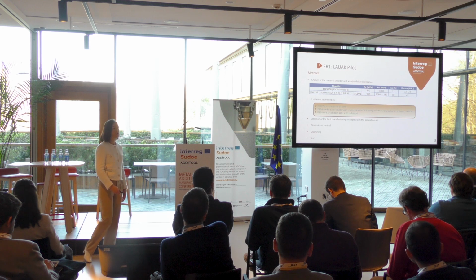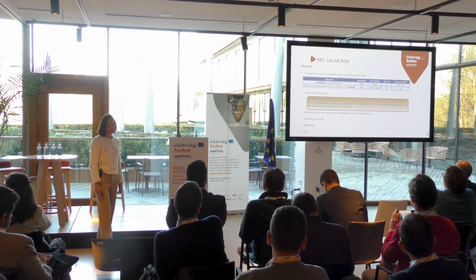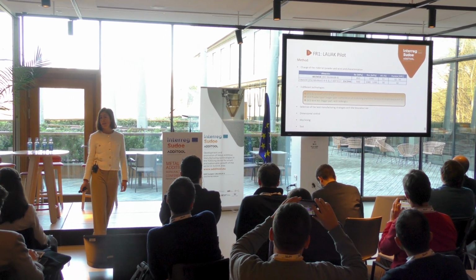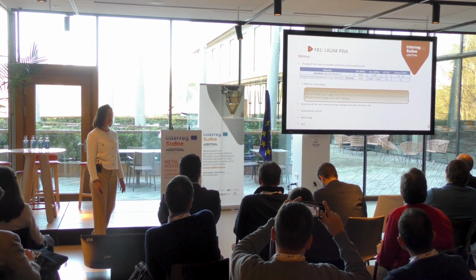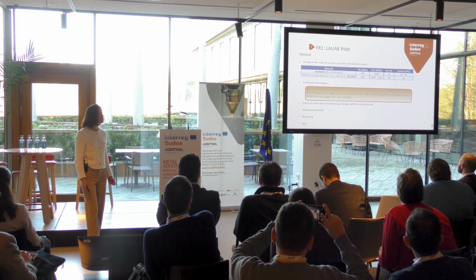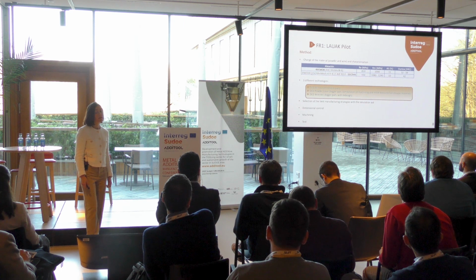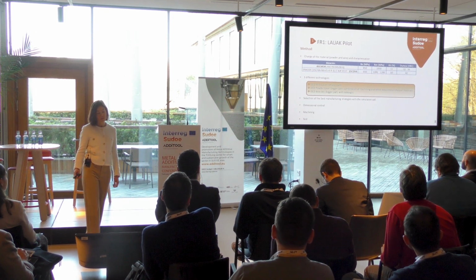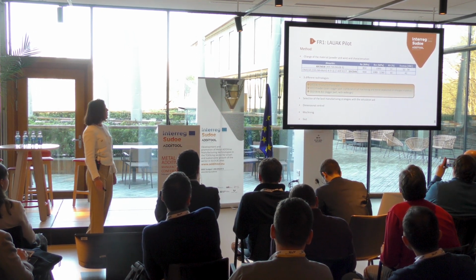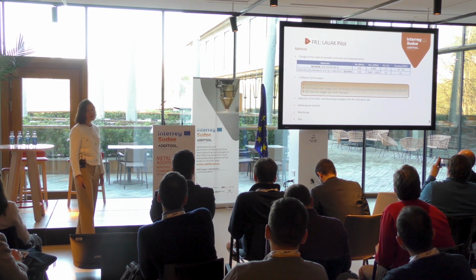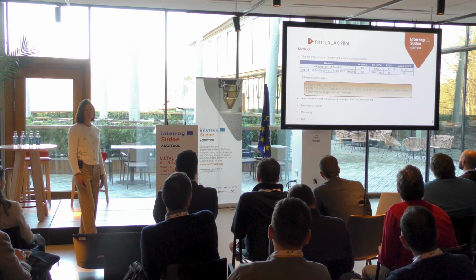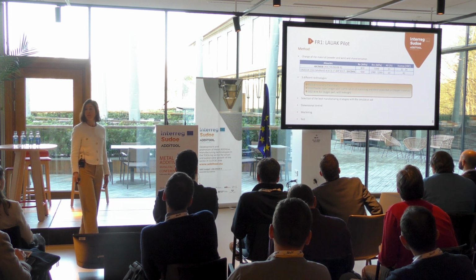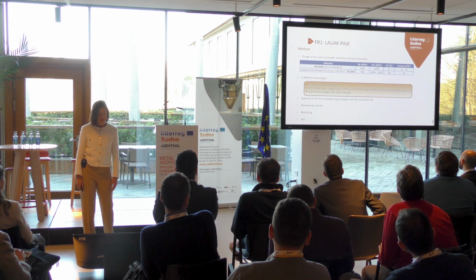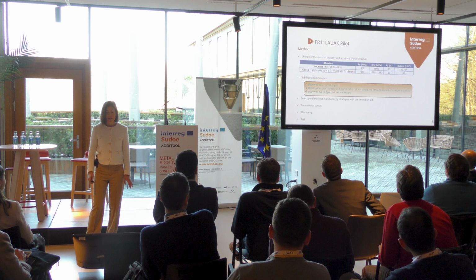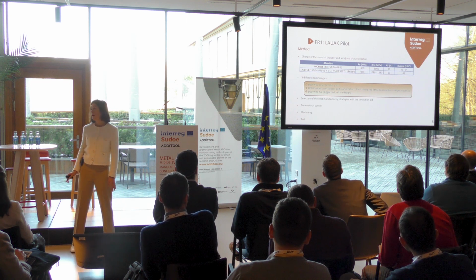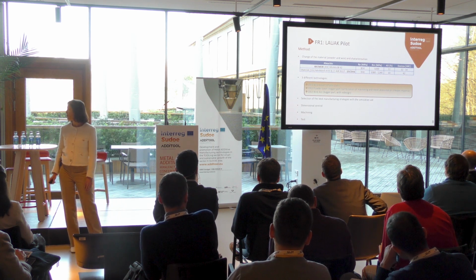The methodology followed started with a selection of material, because the original material is not weldable. So we substituted it with another high-strength material, taking into account that the mechanical properties were similar. The material was the same for both metallic powder and wire.